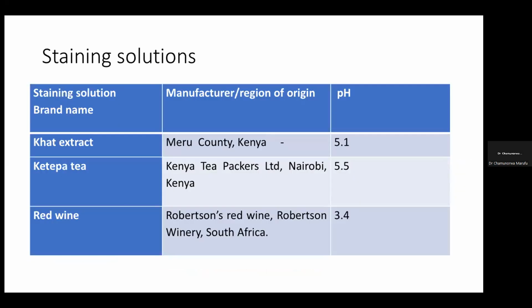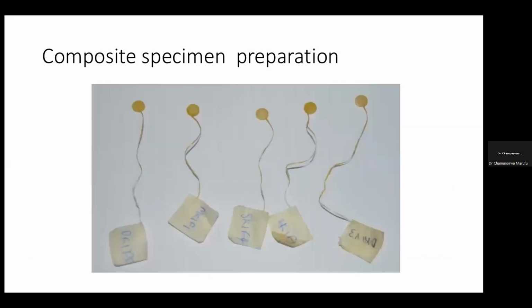So once we got the solutions, we then went on to measure the pH as shown there. So the pH of the tea and the khat is comparable, but that of the red wine is quite low. And then the composite specimen preparation. Again, this was after the study. That's why you find that the composite discs look discolored.